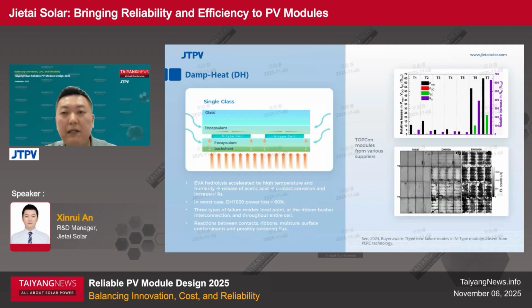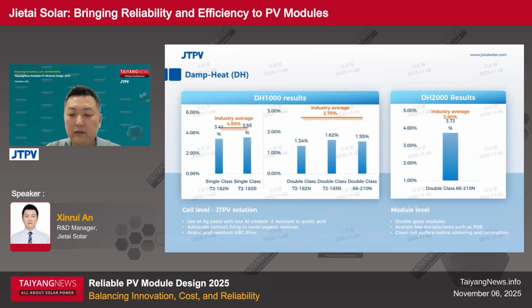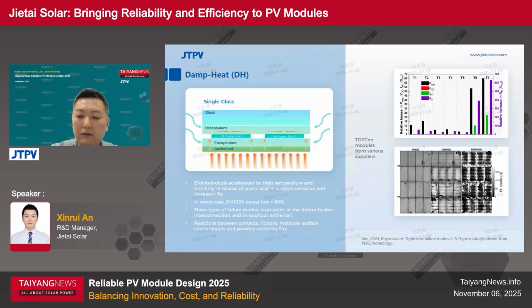Another important reliability metric is the damp heat (DH). It accounts for the module power loss under high temperature and humidity. The main cause for DH is the introduction of acetic acid from encapsulants such as EVA, leading to corroded contacts and increased Rs. This process can be accelerated by high temperature and humidity. For the worst case, up to 60% power loss can be found for some early TOPCon modules after DH1000.